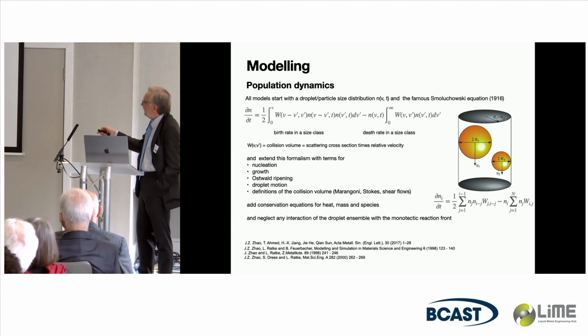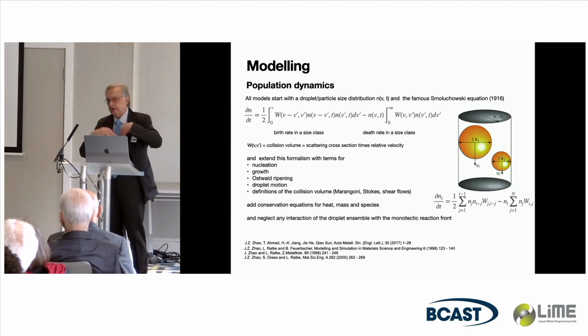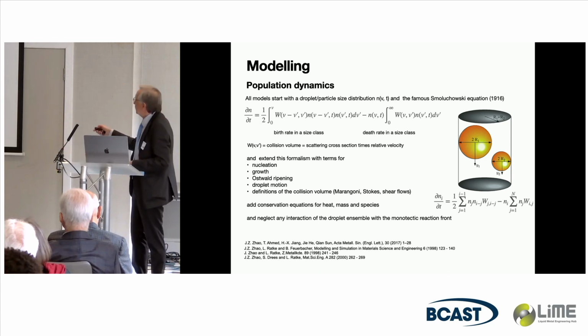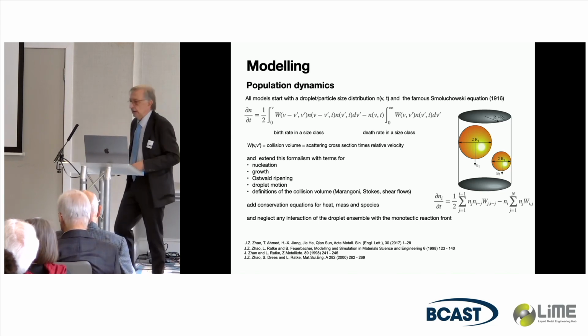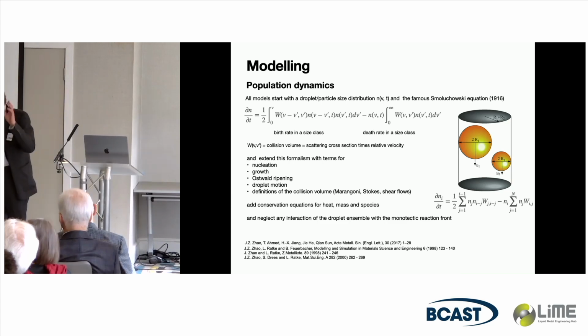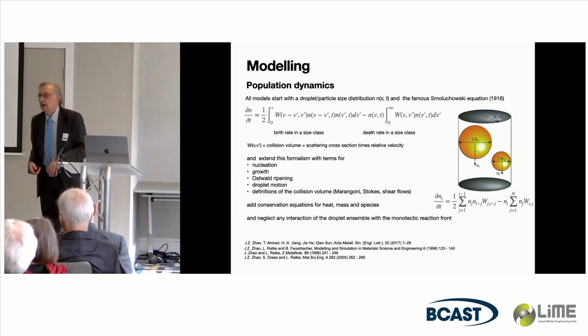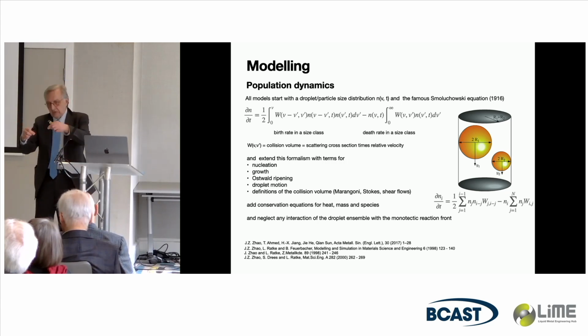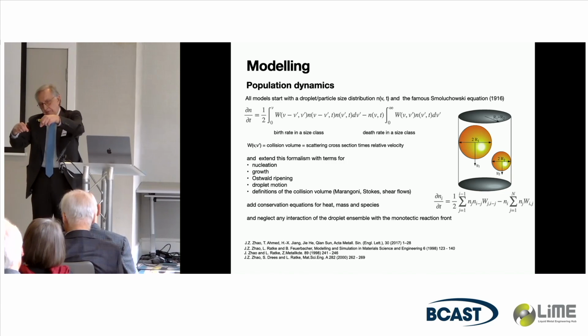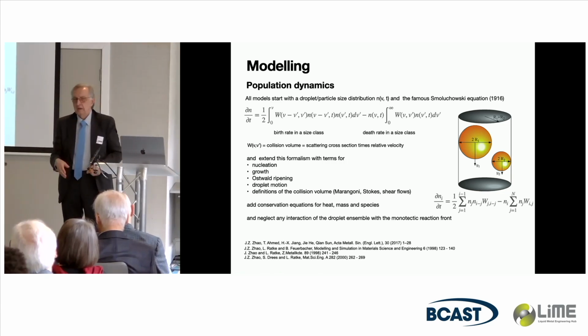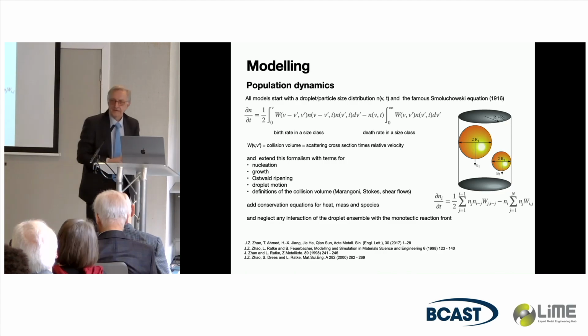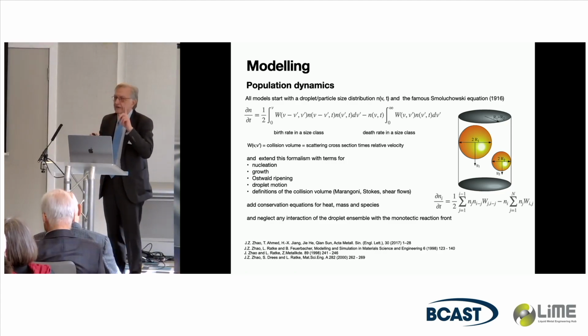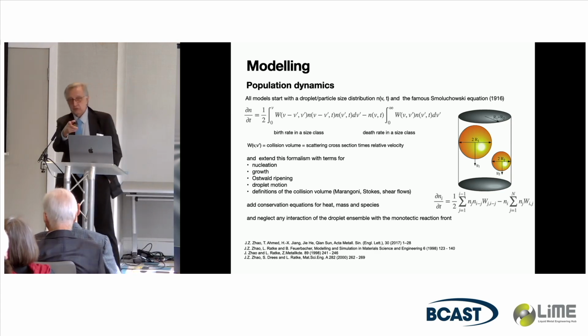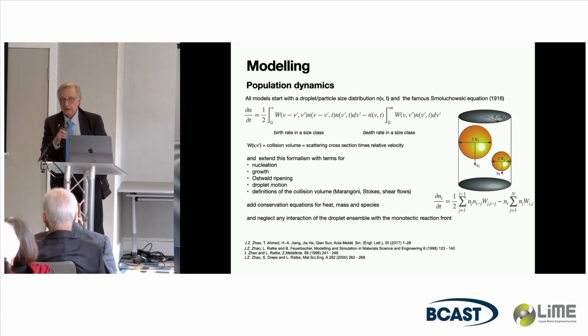So here it's a birth rate, there's a collision volume, which is essentially the scattering cross-section times the relative velocity. So they have different velocities here. And if they would be on straight lines, they would just collide. If you do such an experiment at home, you just take an oil, whatever you have in the kitchen, take water, have a pipette, and make sure that you have one droplet there, take with a pipette a second droplet, and try to coagulate them. You will find out it's not that easy to do. So this interaction is really very complicated. I did that. So to your point this morning, you have to do your own experiments, observations, and make discoveries.